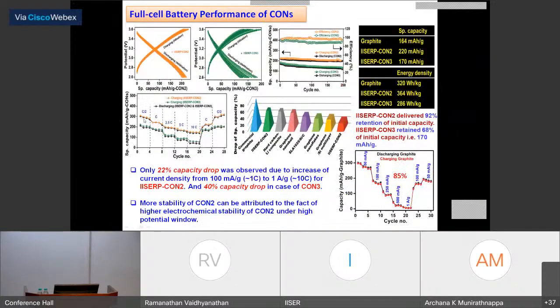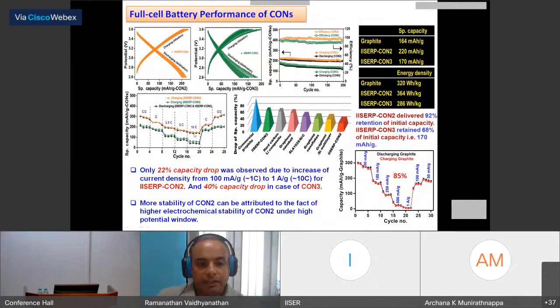Important to see is how much it falls, and we see that the fall is very little for this COF. In comparison, you can see the graphite, a commercial graphite which was used in the same setup in our own lab. You can see that the COF is losing 22% of its capacity, whereas the graphite loses 85% of its capacity when you go from a current density of 100 milliamp per gram to 1 amp per gram. Okay, so that is a very important point to keep in mind.